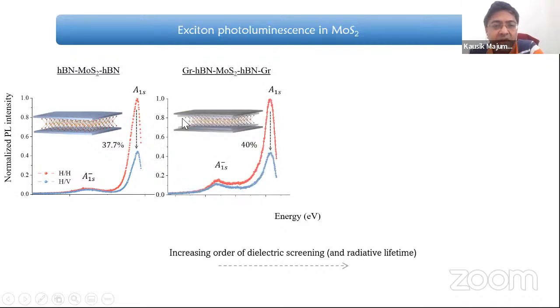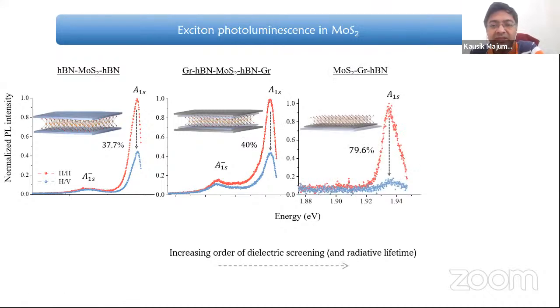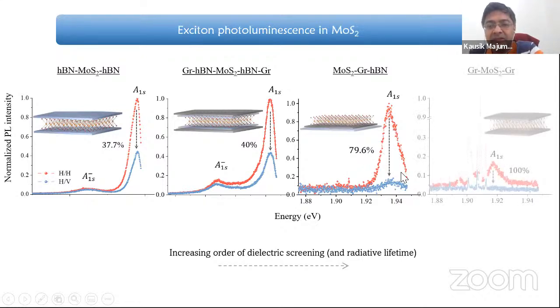The next step that we have is hBN encapsulated MoS2, but then the entire thing is encapsulated by two graphene layers. Here you see it's not really improved much, it's still about 40%. The reason is that although there is screening because of graphene, the lifetime has also increased. So both are sort of canceling each other. The next step we had is one-sided graphene, and there we see a significant enhancement, about 79.6%. And then finally, we had a graphene encapsulated MoS2, where we got exactly 100% polarization.